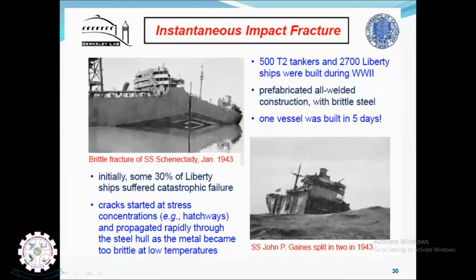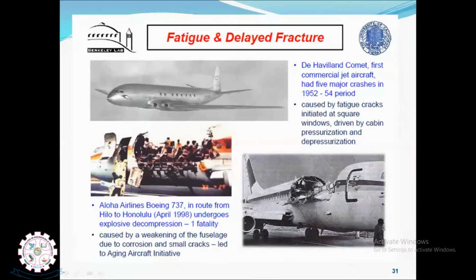And impact load. Five hundred T2 tankers and 2700 Liberty ships were built during the Second World War, and they also got breakage because of the impact factor, sudden load. If the material is not able to withstand the impact load, then sudden breakage leads to huge damage. At the same time, fatigue fracture. The de Havilland, the first commercial jet aircraft, had 5 major crashes in the 1952-54 period, caused by fatigue cracks initiated at the square windows.